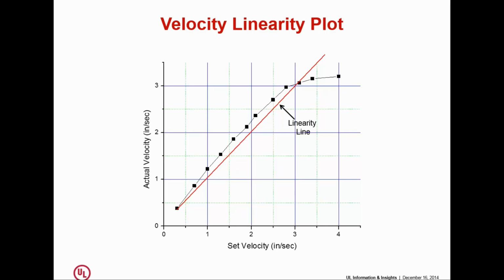And what you'll get is a curve that looks like this. And you'll notice that the actual performance of this machine tracks pretty well against the theoretical line until you get up near the top, and then you start to level off. And this happens with every machine that I've ever worked on. In some cases, it starts a lot earlier, which is not good. You'd like it to start late in the game, but at the very least, it's going to happen when you get out here. So these are things that you really want to know about your machine rather than assume.